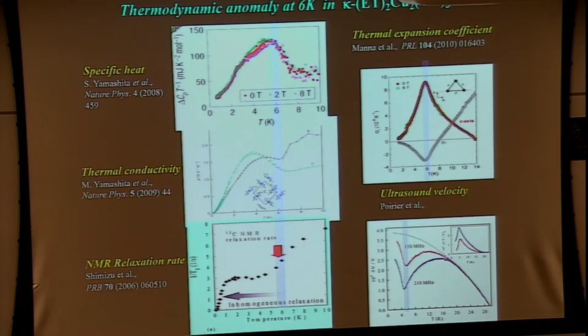Okay, there are several mysterious results, but here I'd like to show you one key result which is still an open question. That is the anomaly that occurs at 6 Kelvin. We call this the 6 Kelvin anomaly. Around 6 Kelvin, or 5 Kelvin, 7 Kelvin, in this temperature range, various anomalies occur in various quantities. For example, in specific heat a broad hump occurs, and thermal conductivity shows some kink in this temperature range. This is a different sample, so it is sample dependent.